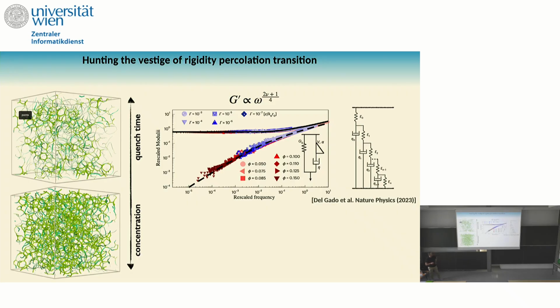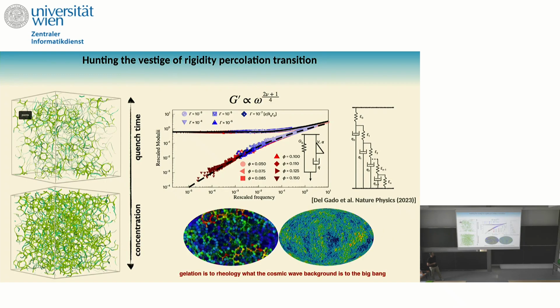So by using this type of model, what we can show is that you can get back the frequency dependence of your moduli, and this goes back to your first question about the time dependence. And you can show that the frequency dependence of the modulus scales again with this critical exponent nu that I showed you before. So again, the critical exponent of the rigidity percolation defines the elasticity for the plateau modulus, but also the viscoelastic frequency dependence. It is very, very important.